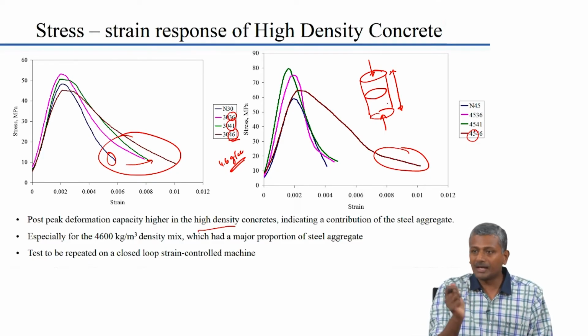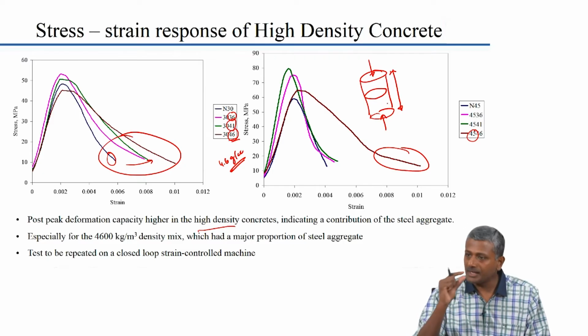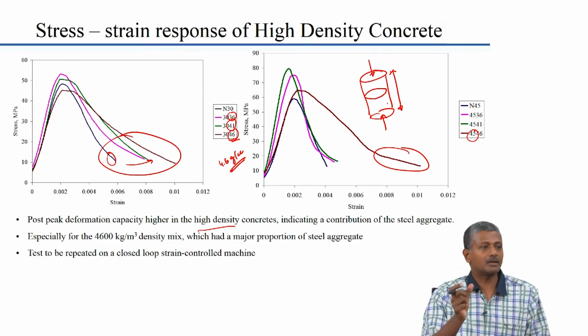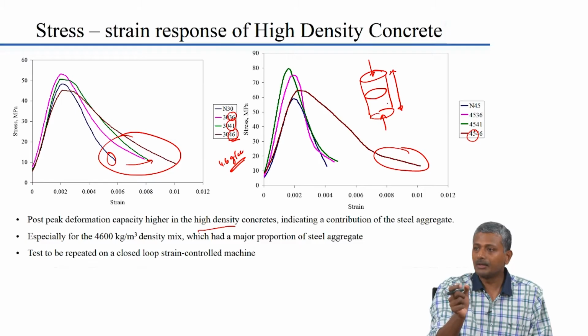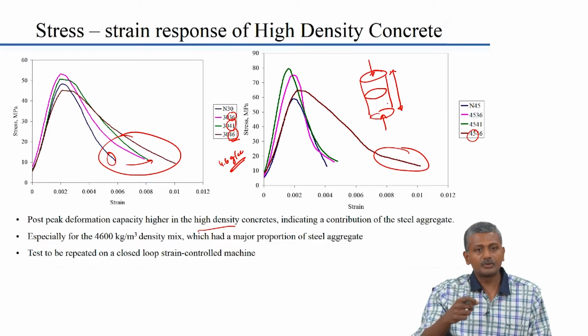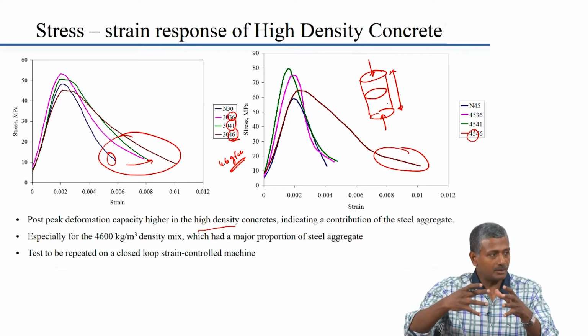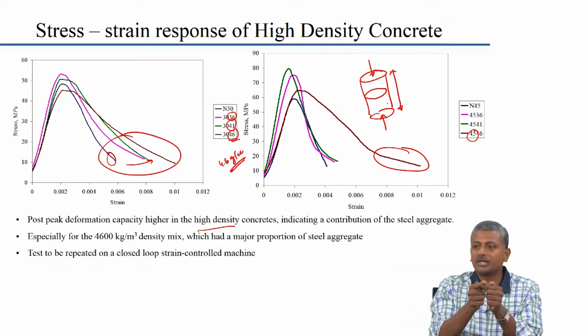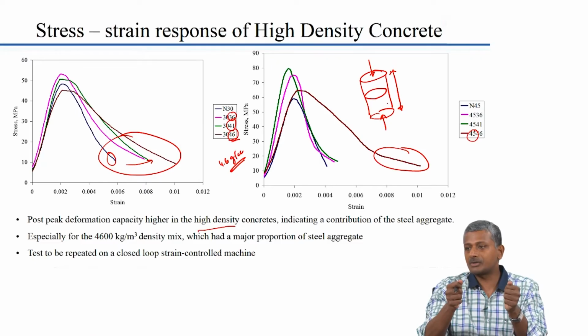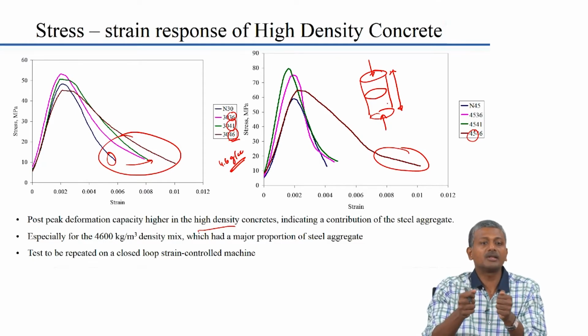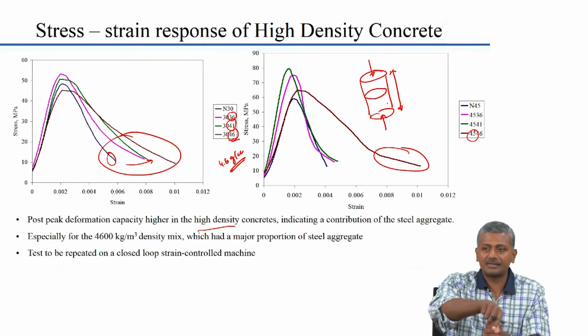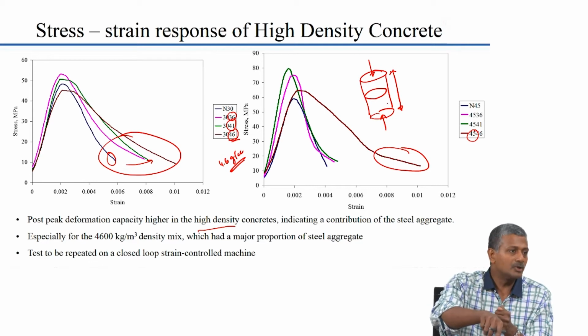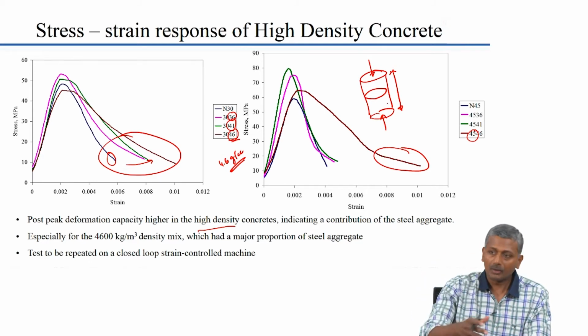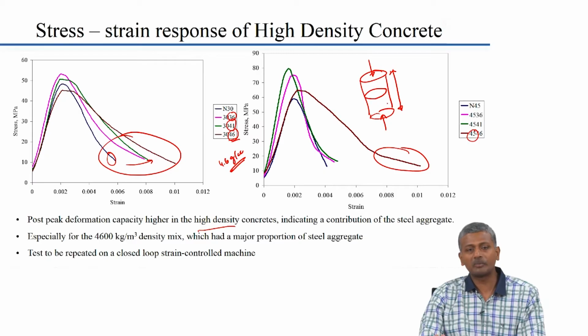So, for that, what people have done is they have used chains along the circumference and connected a length deformation gauge, a clip gauge, to the chain. As the concrete expands laterally, the clip gauge in the chain starts getting subjected to tensile strains. Then we start recording the strains directly, and that is sent as an input into the system to control the rate of the next load. Now, this is possible with the equipment that we have.